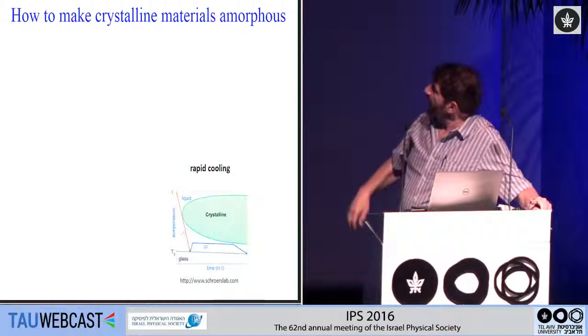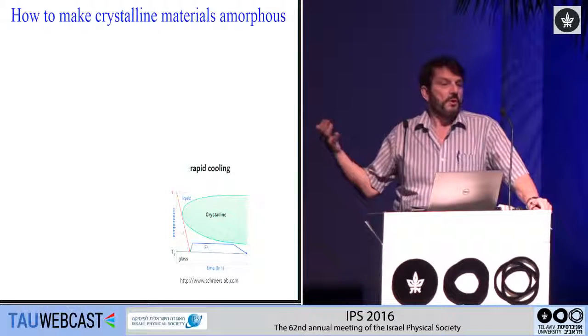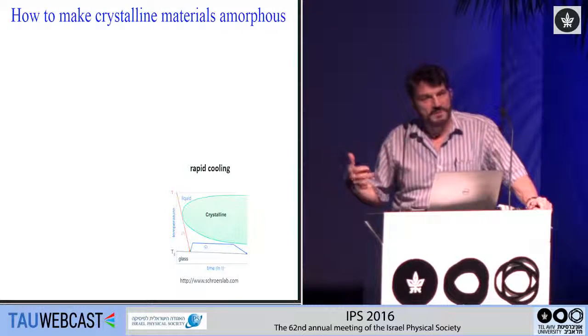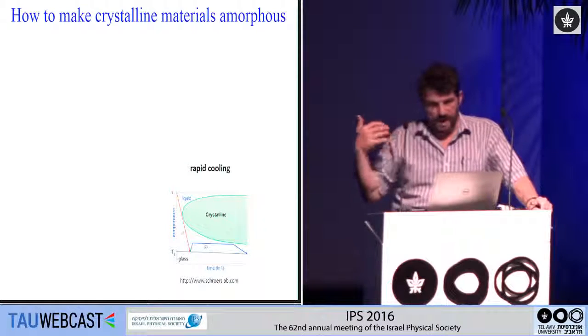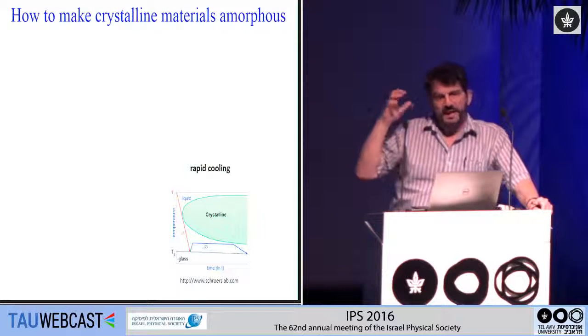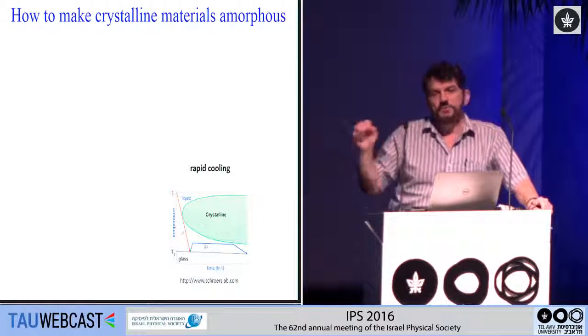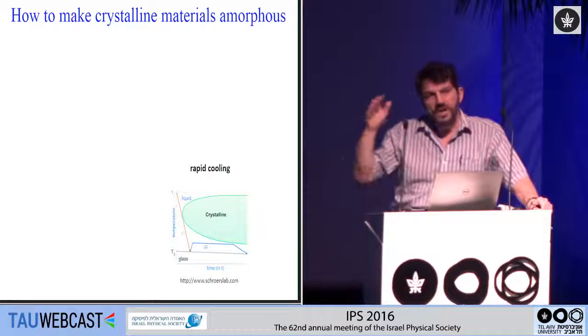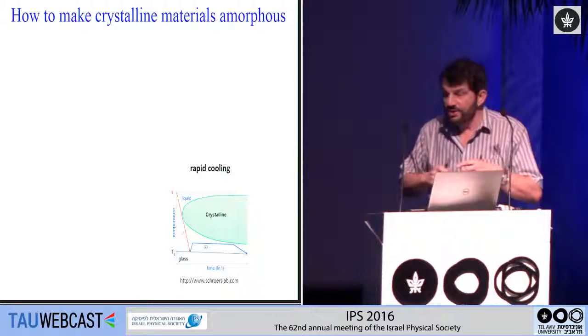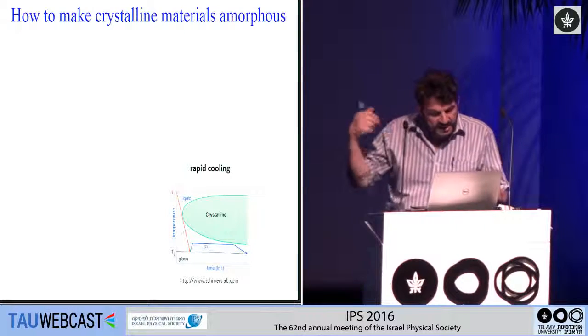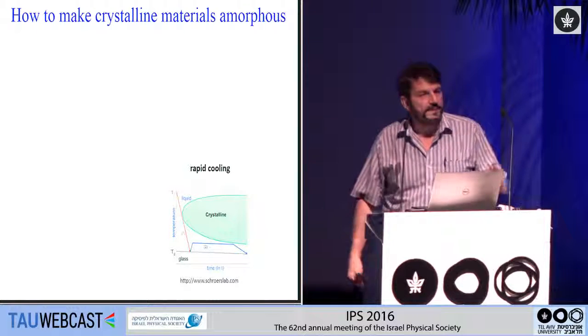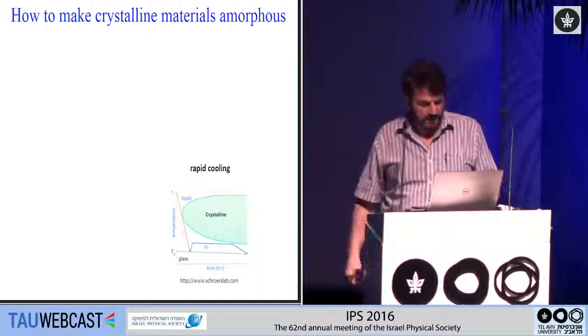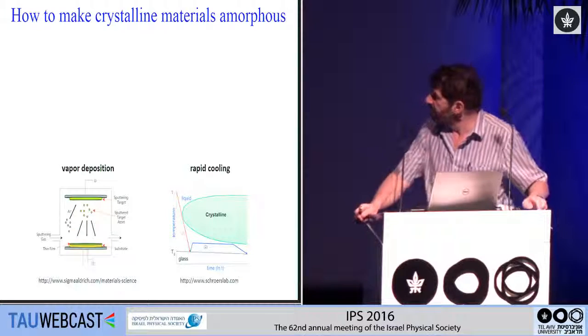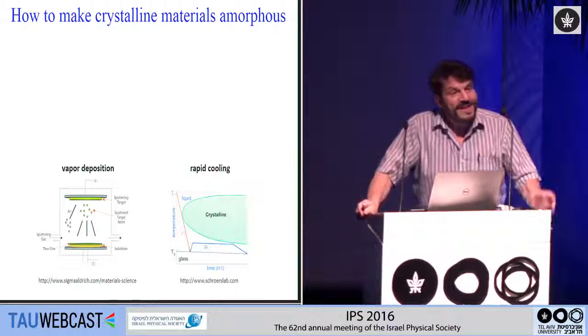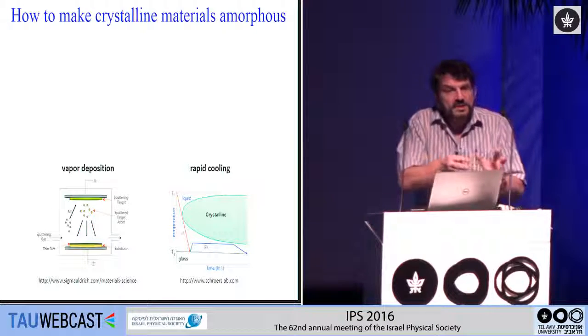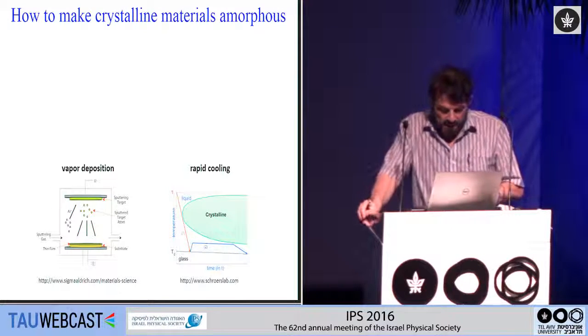So how do you normally do this? Well, you can make amorphous materials like amorphous metals by very, very rapidly cooling. But to rapidly cool something and make it amorphous, you have to avoid the crystallization region. And that's actually fairly difficult. Nevertheless, people are becoming very adept at splat cooling, rapid cooling of metals to make them amorphous. You can do vapor deposition, same thing. You're depositing things so rapidly that you can make them amorphous.